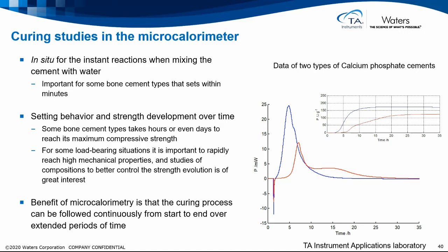So the benefit of microcalorimetry is that the curing process can be followed continuously from start to end over extended periods of time. The example here shows two types of calcium phosphate cement, and you can see they cure completely differently. One is very fast and one is slower, and it also cures over a longer time.